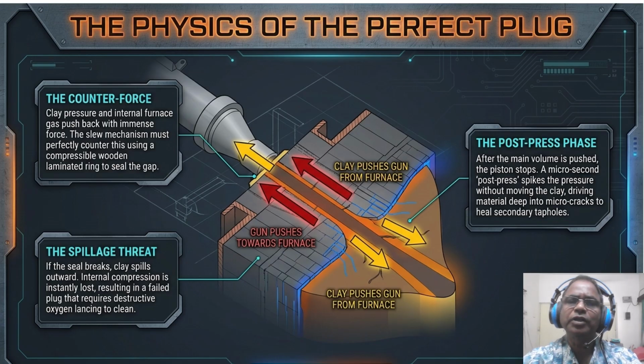After the main volume of the clay is pushed by the ram, we hit a microsecond post press spike. This drives clay deep into the secondary micro cracks to heal the secondary taphole. If this seal breaks, as shown in the spillage thread box, internal compression is lost. The result is a failed plug that will require destructive oxygen lancing to open. We use this mechanical force to mold the internal valve, ensuring that when we drill the next time, the clay has cured into a rigid, predictable cylinder.